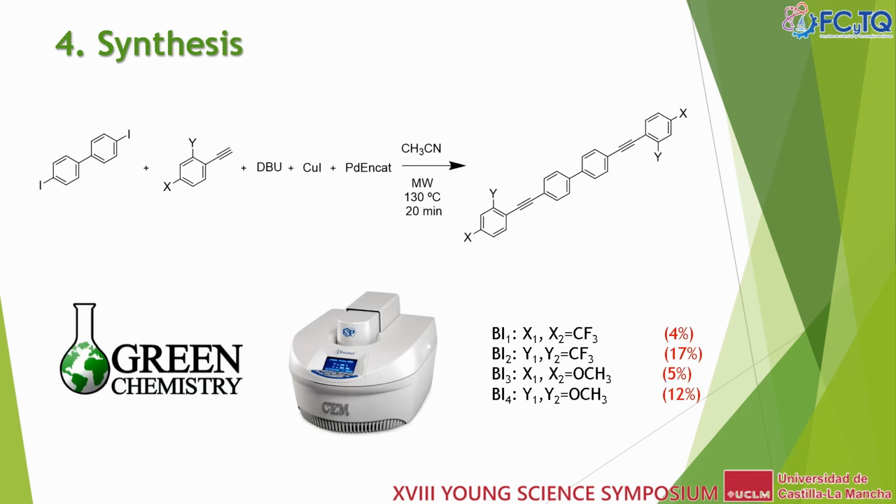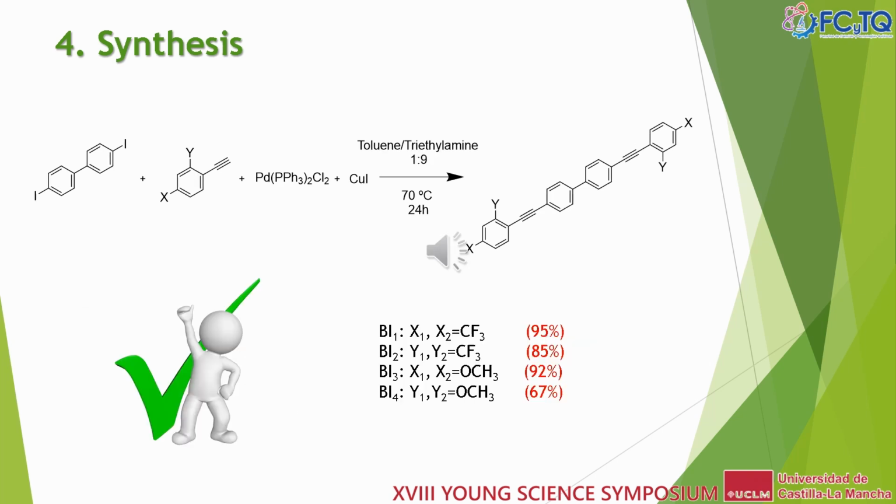Synthesis was performed by a Sonogashira cross-coupling reaction to 4,4'-diiodobiphenyl. Firstly, the reaction was carried out under microwave irradiation, using less time and solvent volume, which makes it an environmentally benign synthesis. The compounds were successfully obtained, but due to the low yields, the synthesis was carried out under classical heating, improving the yield of the products as a result.